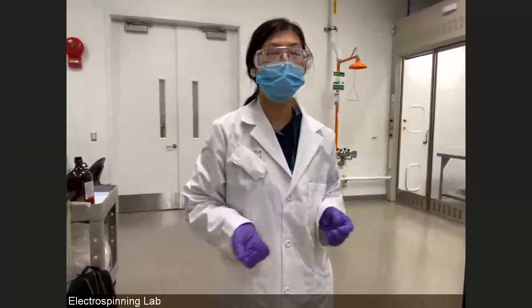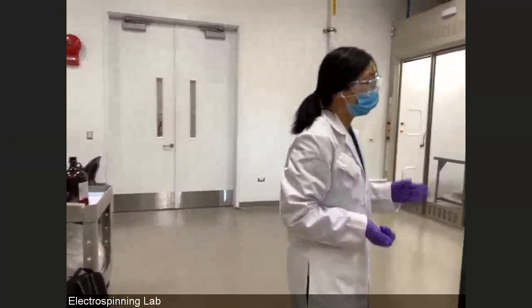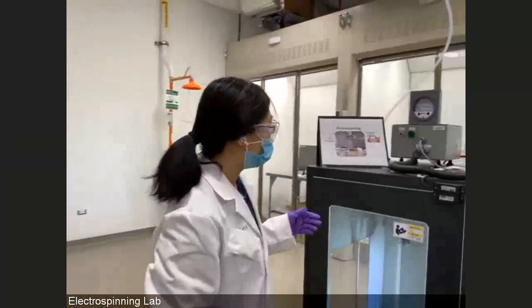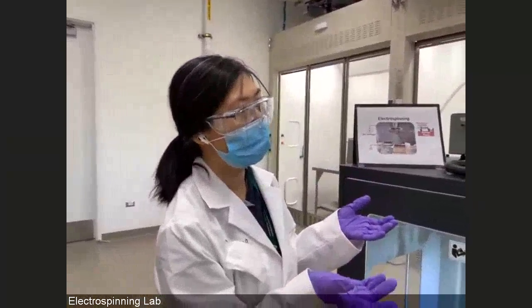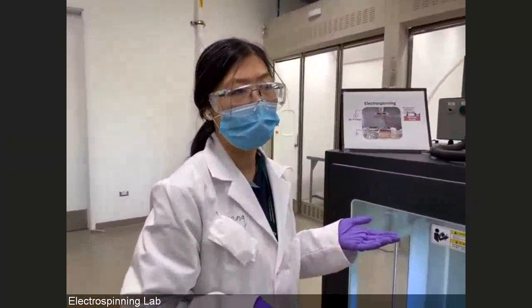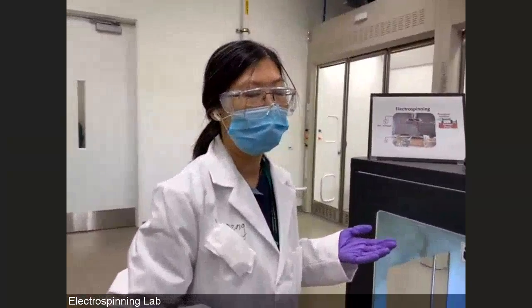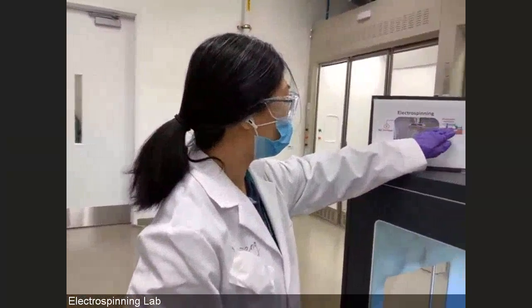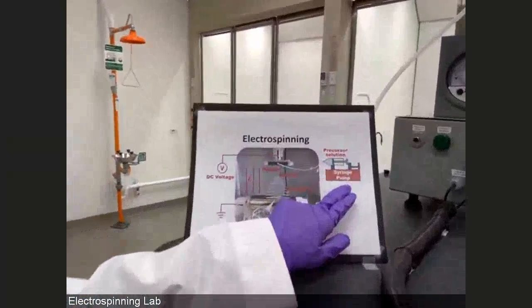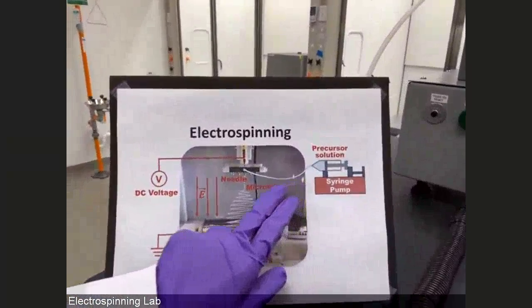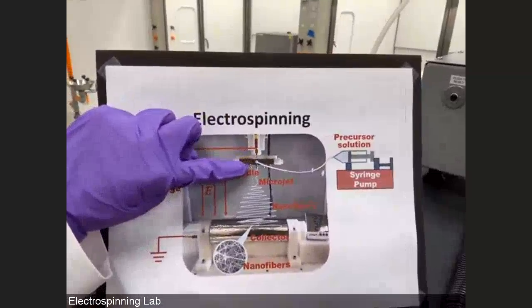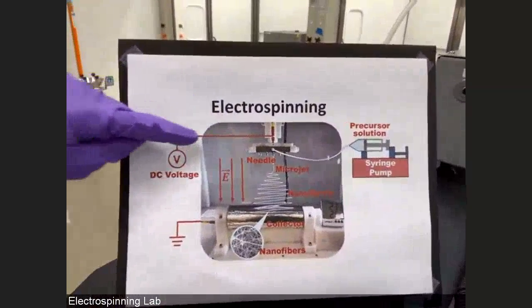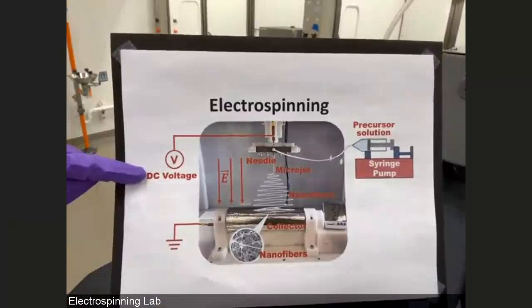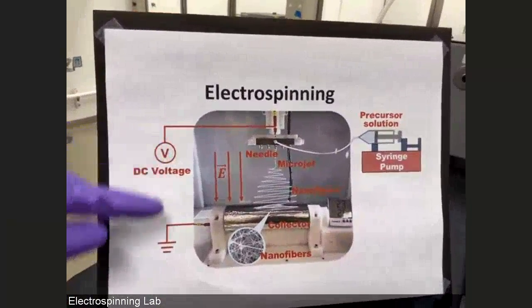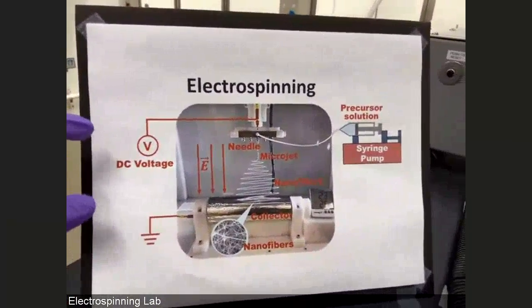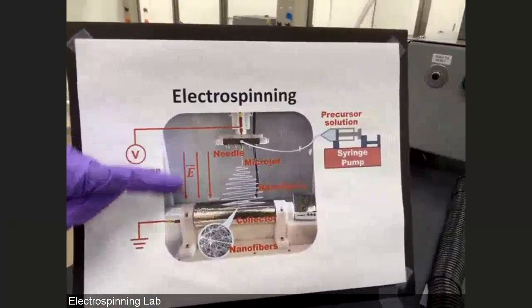How does electrospinning work? If you wanted to set up an electrospinning experiment, first you dissolve your polymer into solvent. Usually we use organic solvent, but you can also use water-based solvent. And then you feed the solution into a syringe pump, and then you introduce that solution through a tubing to a very thin needle here. Now you apply very high voltage to the needle, and you ground your collector that is facing the needle. In this way, you generate a strong electric field between the needle and the collector.